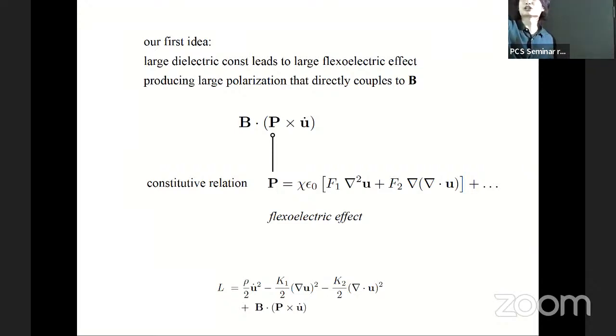It turns out that a large dielectric constant will lead to a large flexoelectric effect, which I'll explain in the next slide. The flexoelectric effect produces a large polarization. And because polarization is electric charge, the motion of electric charge can couple to a magnetic field. It's captured by this term in the Lagrangian, or say in the Hamiltonian, where the Lorentz force can be expressed like this: a polarization, and when the acoustic phonon is moving, with u dot, and it has a polarization, it will generate a Lorentz force of this form in the Lagrangian. So the Lagrangian will have the usual terms for the phonon as well as this term due to the Lorentz force of the polarization. And the flexoelectric effect means when there is some acoustic deformation, like a second order gradient of u, the acoustic displacement, it will generate polarization, and it's proportional to the dielectric constant.